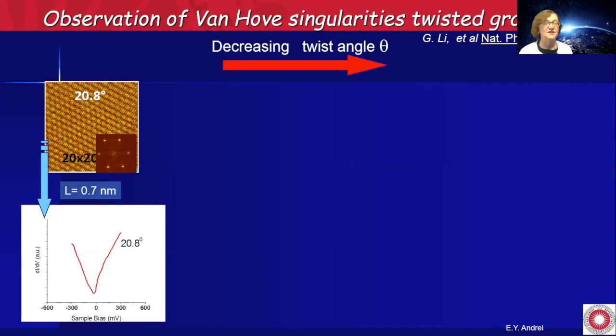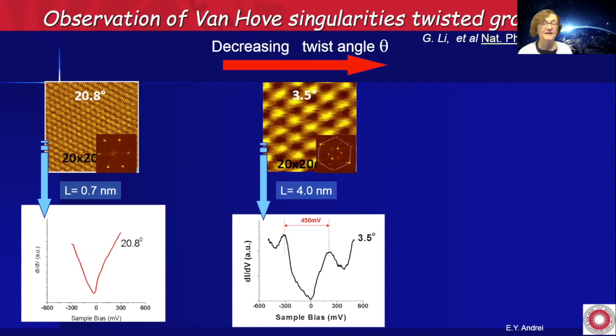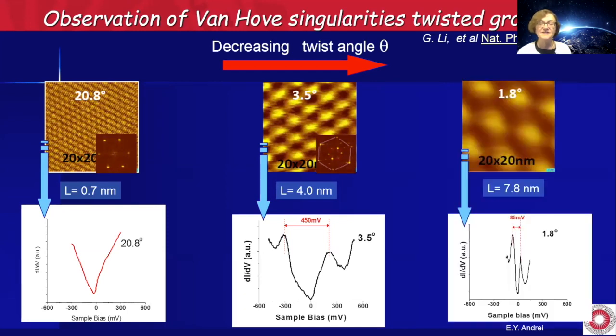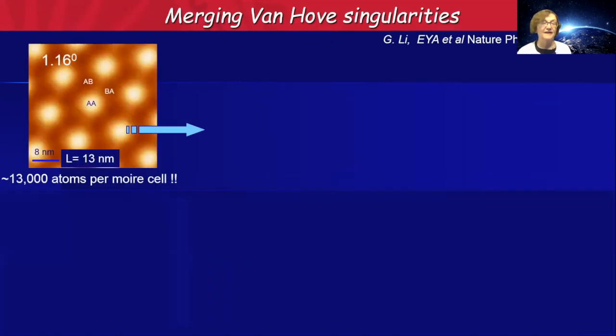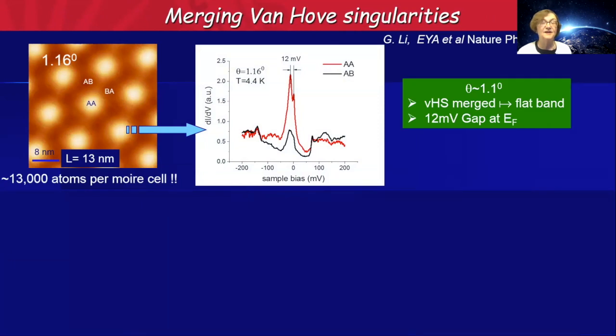In this case, it looks very much like monolayer graphene, but then when we go to smaller and smaller angles, here we have an angle of 3.5 degrees, suddenly you see these peaks, and as you keep decreasing the twist angle, the peaks keep coming closer and closer together. Eventually you come to a point where the peaks actually merge together. This is 1.1 degrees, a twist angle that we call the magic angle. And here the Fermi energy is 0. We have a small gap in the Fermi energy, which is very intriguing because it tells us maybe there are correlation effects going on. This is what we thought at the time, although we couldn't do much more than this.